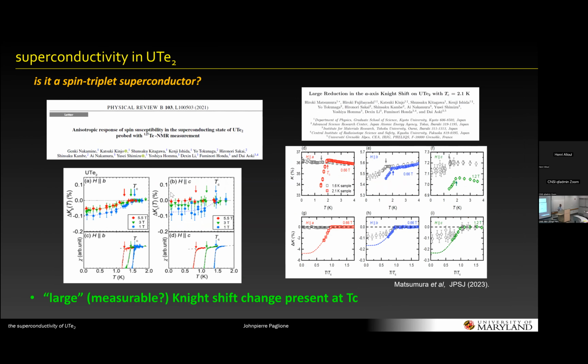But of course, NMR has been studied by a few groups, and there's been a dozen papers on NMR studies, Knight shift. So there's a very small change in the Knight shift, and this has also been a sort of a point of debate in terms of interpreting this observable change with small change in terms of what order parameter is there. And there's some experts in the audience here that can probably answer better what this all means, but I would say it's a small change. It's a matter of a few percent. So that's, even in Aoki's group, they claim this is consistent with a triplet state, and I think they might point to a fully gapped P-wave state for their interpretation.